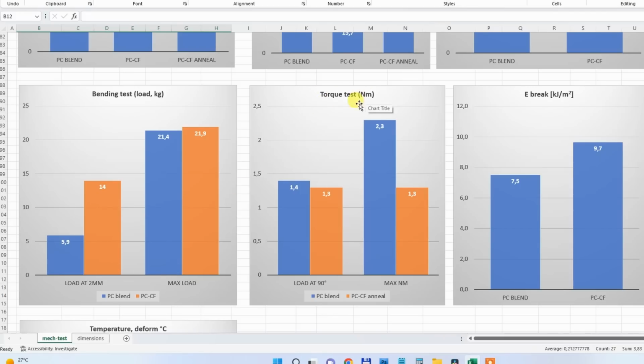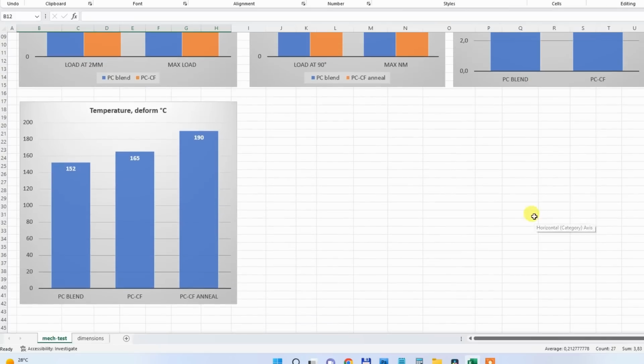And similar with the torque test, this is more important, the load at a 90-degree rotation. Very similar numbers. This is not so important. I mean, I don't need 2 rotations. This is again not an elasticity material. And here they were very equal. Breaking energy, well, the carbon fiber version was a little bit better, maybe 30%.